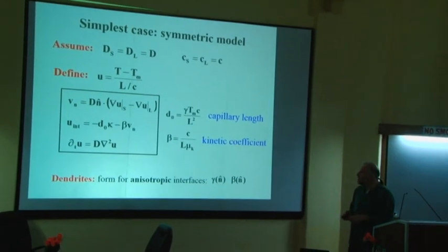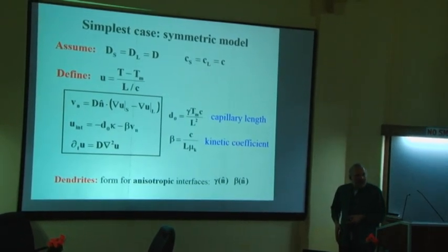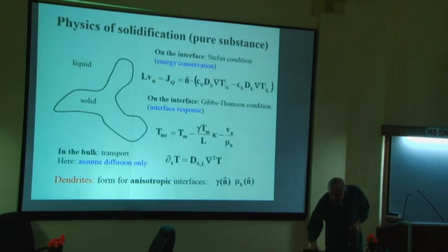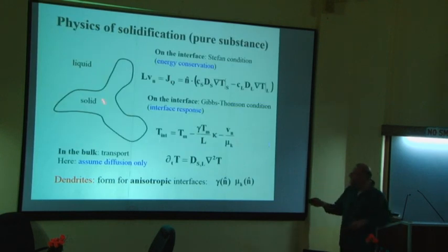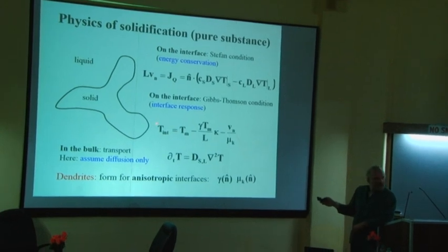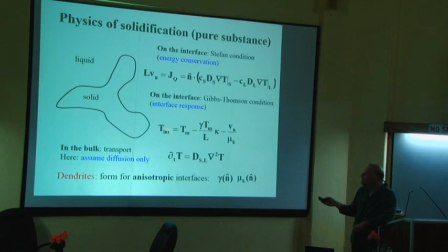And then you can imagine how one would solve this mathematically. So in this formulation, what do you do? Well, if I go back to the previous picture, suppose that you have a given shape of the crystal and you know the interface velocity from the previous time step. Then you can plug this in here. So you can calculate the boundary condition for the temperature at the interface.